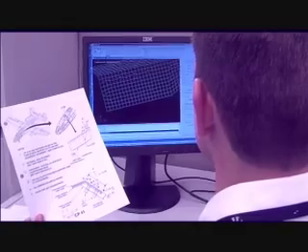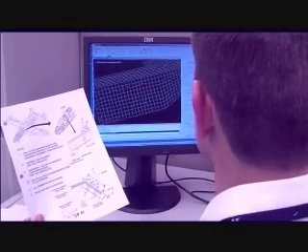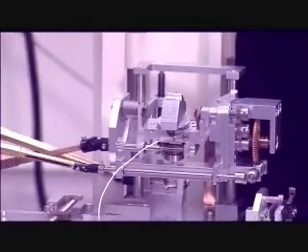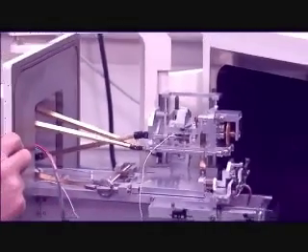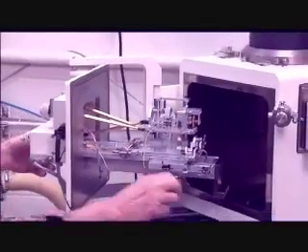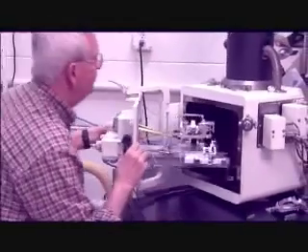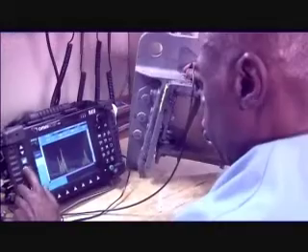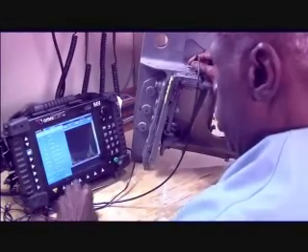The loading and cycling of the test procedure is carefully planned so as to validate an extended structural service life goal, including a scatter factor of 2. At the completion of the test, a destructive teardown inspection is conducted to closely examine damage to the structure so as to proactively design repairs, reinforcements, and inspections if necessary to preclude structural failure. This teardown inspection process includes sophisticated mag particle and dye penetrant inspection of fastener holes, in situ, as well as microscopic fractographic analysis of fracture faces.